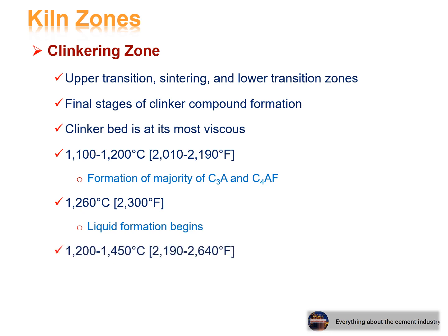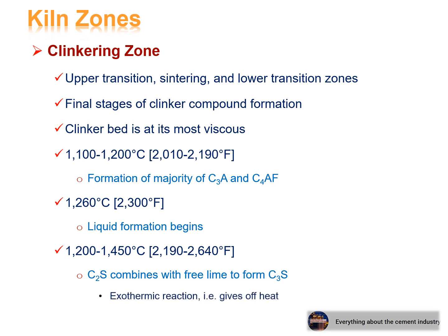1200 to 1450 degrees: C2S combines with free lime to form C3S. Exothermic reaction, gives off heat. Disappearance of free lime.